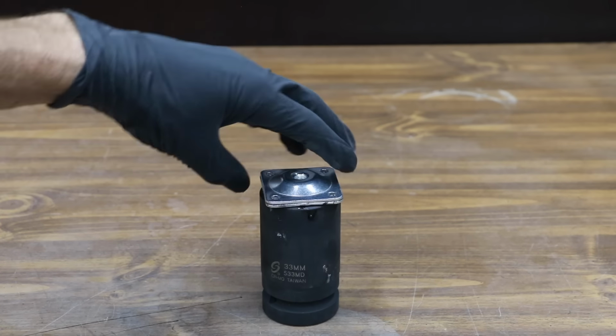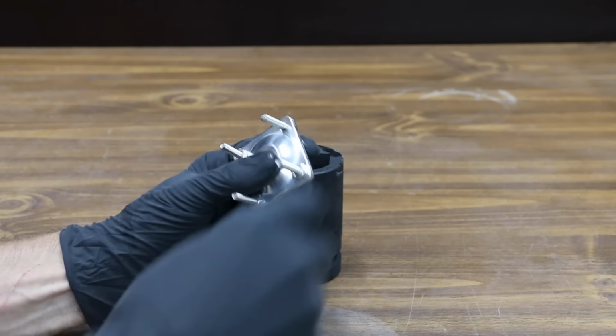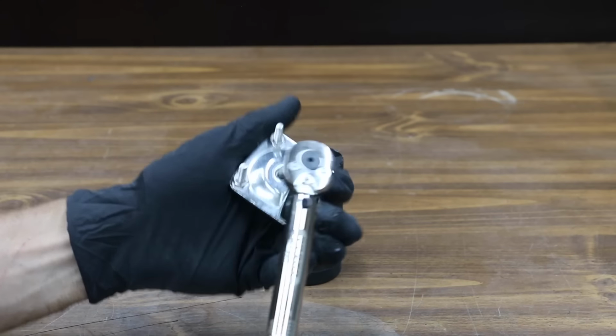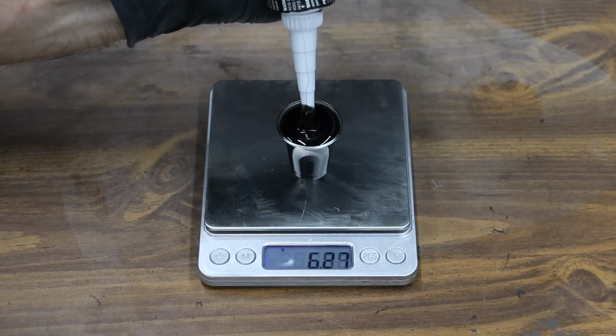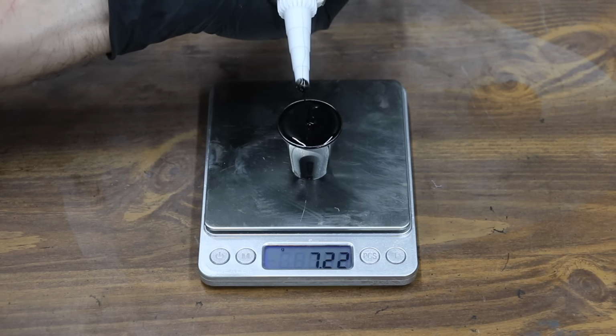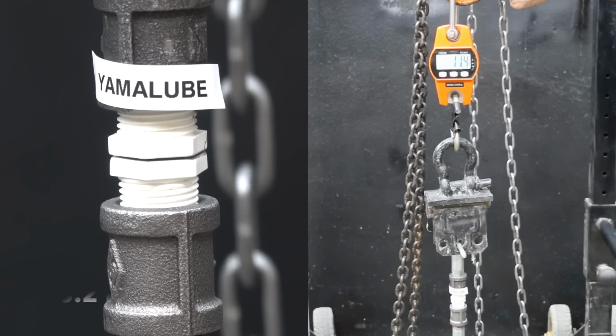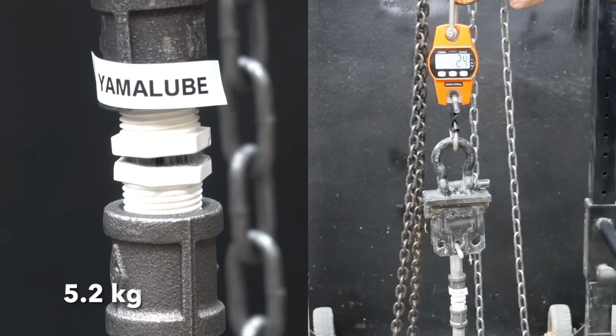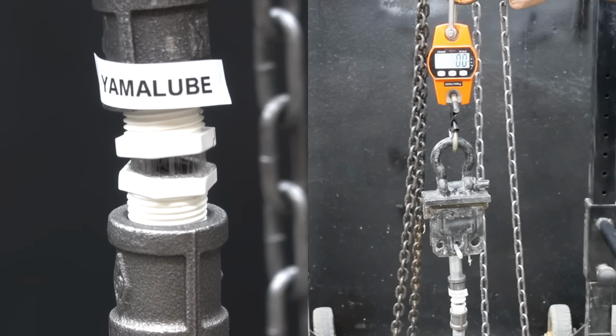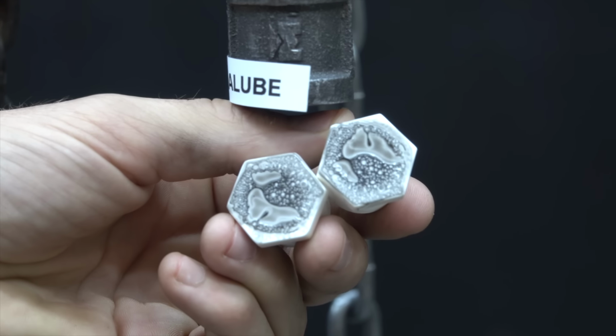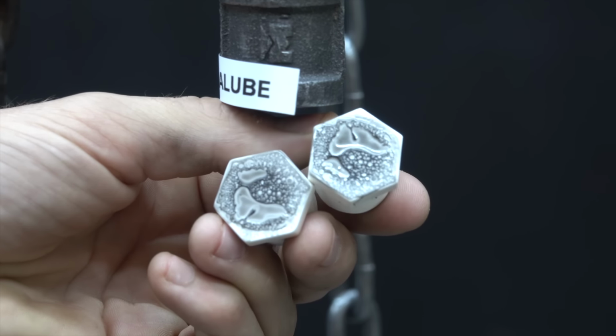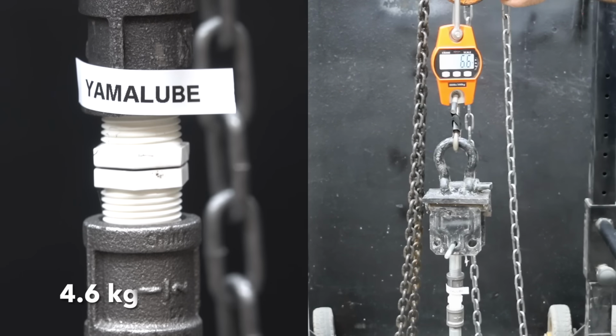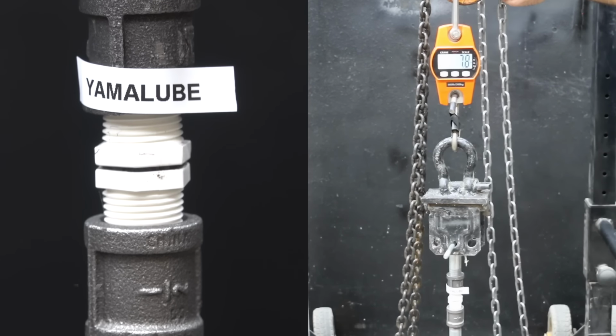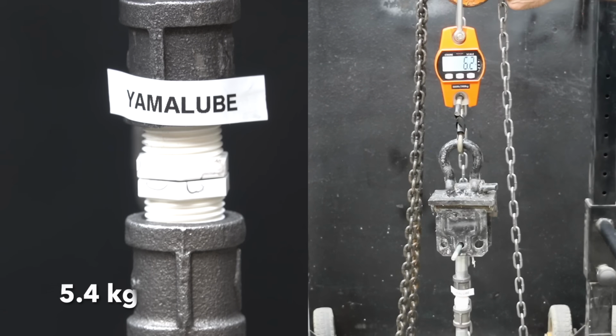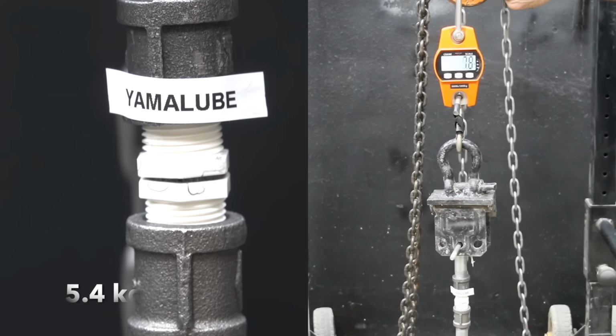Unlike the other products, which are silicone-based RTVs, the Yamalube is an adhesive liquid gasket. It has a very low viscosity and it's runny. And the Yamalube actually melted the plastic cup after about 5 minutes. And the Yamalube didn't perform well in the first test at only 11.4 pounds. However, the Yamalube did fully cure across the entire surface area of the PVC end cap. On the second test piece, the Yamalube performed almost the same as the first at 10.2 pounds. 12 pounds in the third test piece for an overall average of 11.2 pounds for the Yamalube.